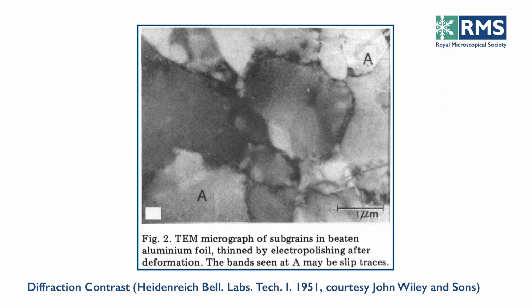Right about the same time, which was about 1949 or 1950, there appeared in the literature a transmission electron micrograph by Heidenreich at Bell Telephone. A TEM micrograph of subgrains in beaten aluminium foil. And that's essentially how we got into electron microscopy of deformed metals.